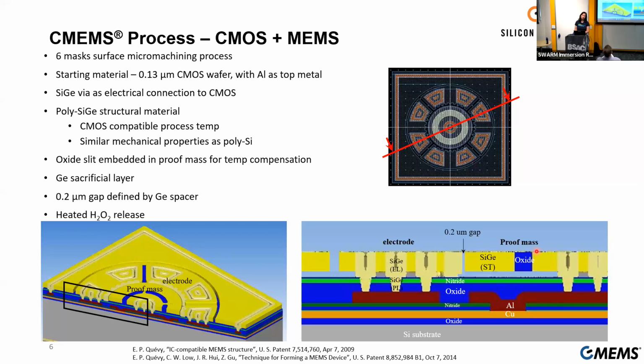The reason that we use silicon germanium as the structural material is because it can be deposited at a CMOS compatible process temperature. So whenever we do a deposition, the CMOS underneath will not be damaged. And also polysilicon germanium has very similar mechanical properties to polysilicon, which is good for the quality factor.